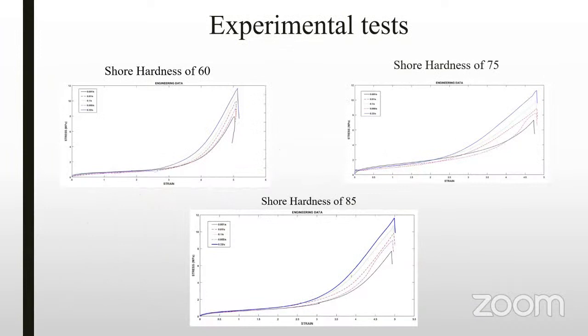In this slide, we can see the engineering stress versus engineering strain curves for different shore hardnesses of polyurethane in different strain rates. As we can see, by increasing the strain rate, the hardening behavior of the material is increased too, and also by increasing the shore hardness of the material, the maximum stress of the material is increased.